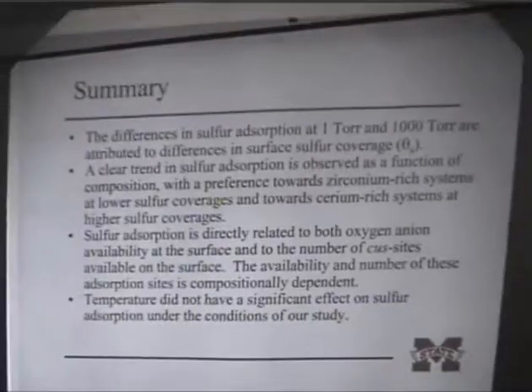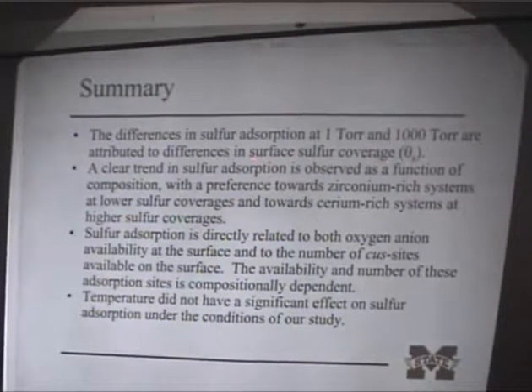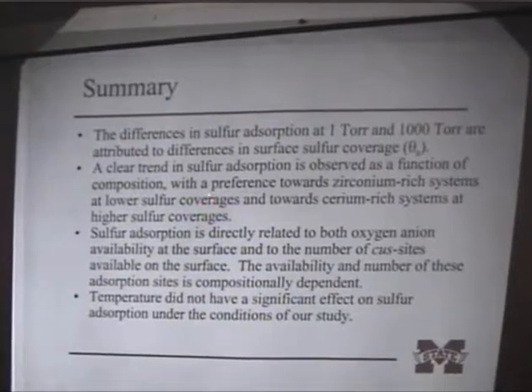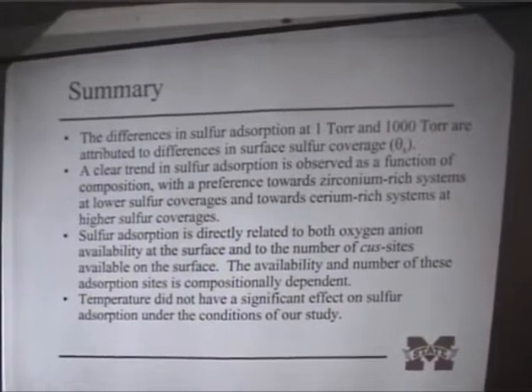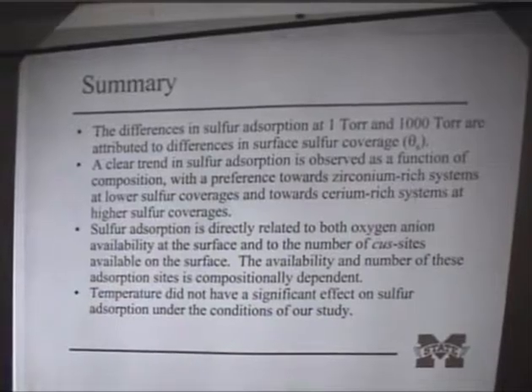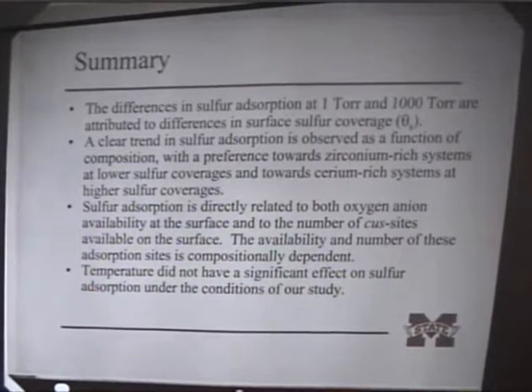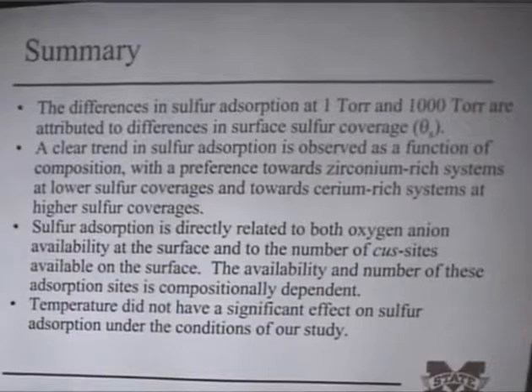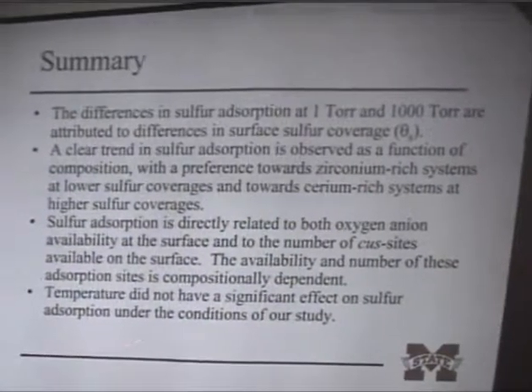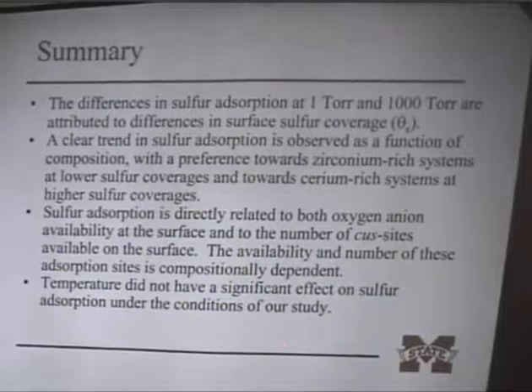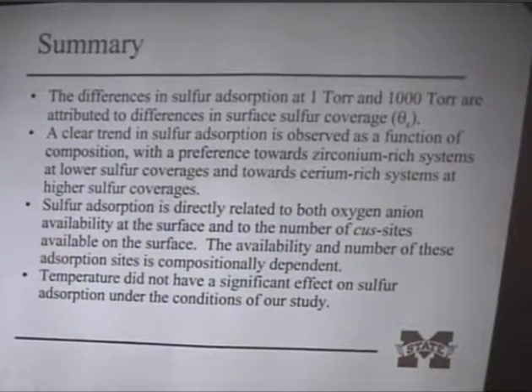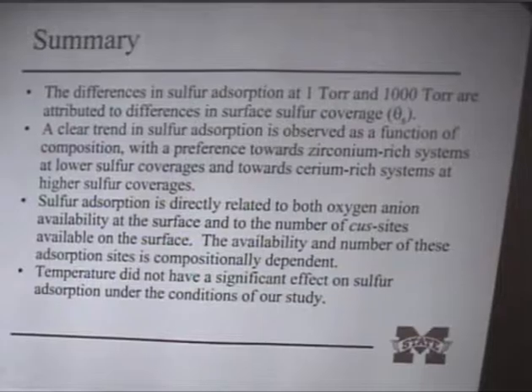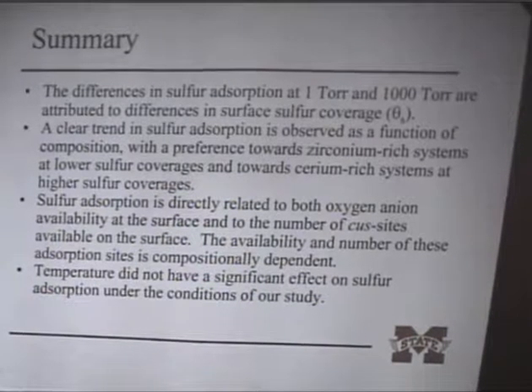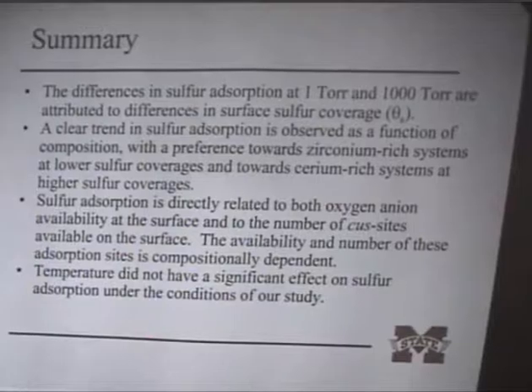So the differences in sulfur adsorption in our experiments are really thought to be differences in surface sulfur coverage. One of the things that we can clearly say is the way SO2 goes down is related to composition, which we think is then related to the amount of oxygen at the surface and the number of vacancies at the surface. Temperature did not have a significant effect on the sulfur adsorption under the conditions of our study, but again, we're looking at this to see if we can track exactly how the species are developing as a function of temperature, and we believe we're going to get some more insight into this phenomenon by looking at those experiments.